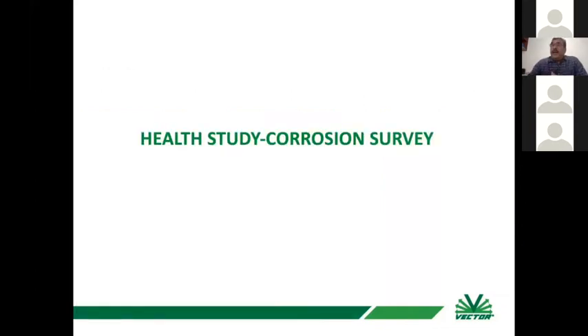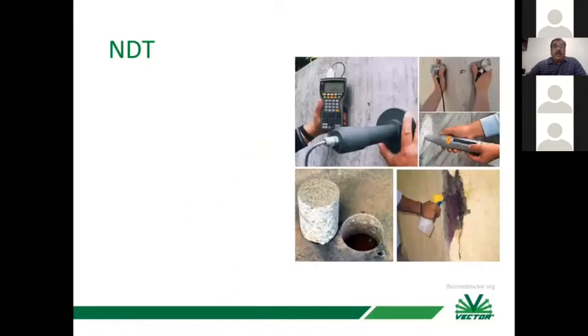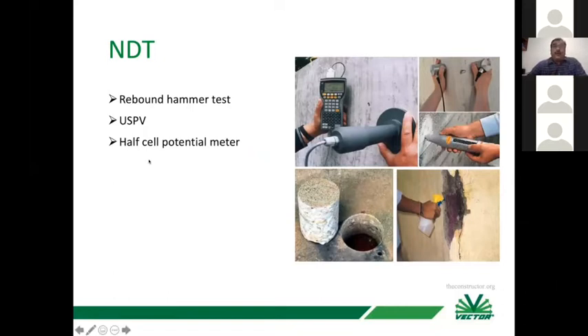And to go for any repair, I will have just one or two slides on the health study, the corrosion survey. When we say I have done NDT, it should not be confined to only UPV and rebound hammer or maximum core strength. You should have a proper corrosion survey. You should find out the reason of damage or distress, cracks, spalling, or whatever failure is there. You have to take a holistic approach of NDT, using half cell potential for corrosion probability. You should know the existing cover, the existing strength, the chemical analysis, how the cracks are there, and